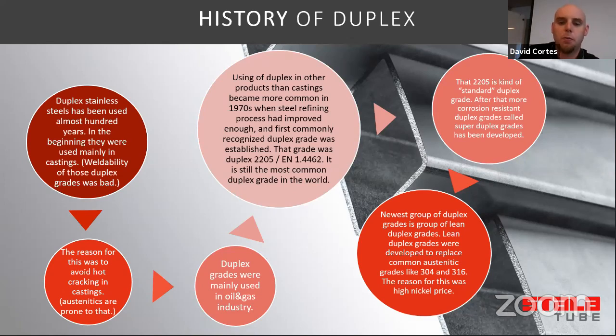And something about the history of duplex, how did this start? So duplex stainless steel has been used almost 100 years. And in the beginning, they were used mainly in castings. And the reason for that was to avoid hot cracking, because the standard material was fully austenitic stainless steel, which is very prone to hot cracking. And the main application was the oil and gas industry, typically valves. Different kinds of valve bodies were cast products. So the use of duplex in other products than castings became more common in the 1970s when the steel refining process had improved enough. And the first commonly recognized duplex grade was established.